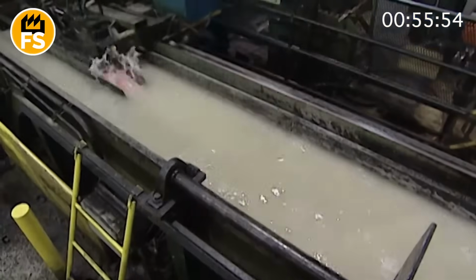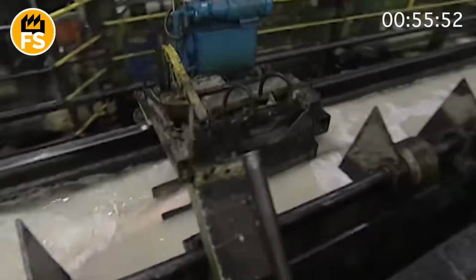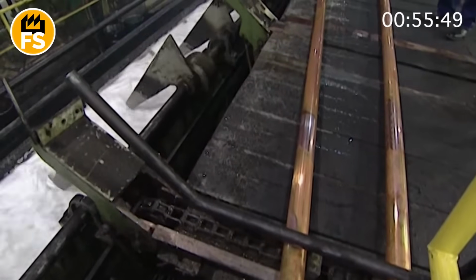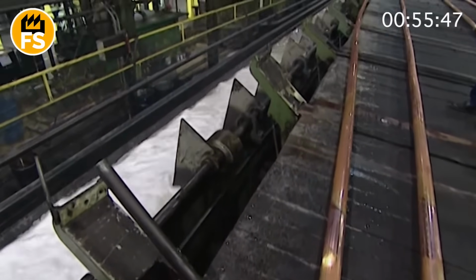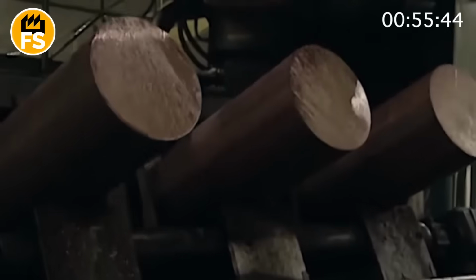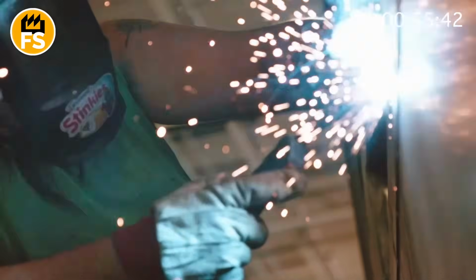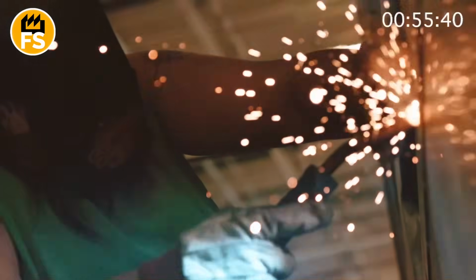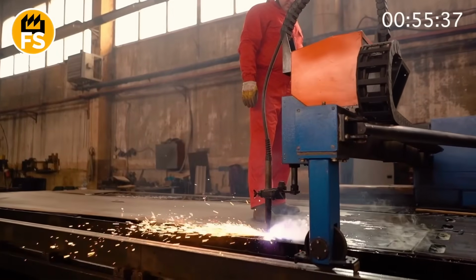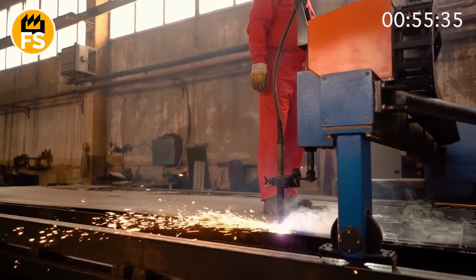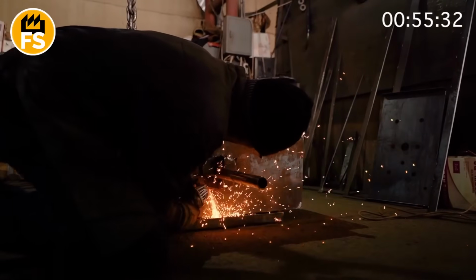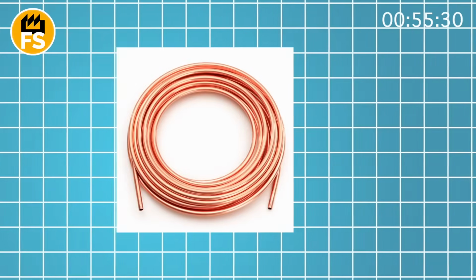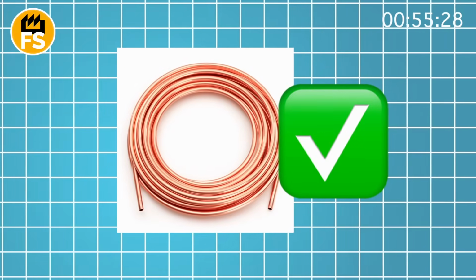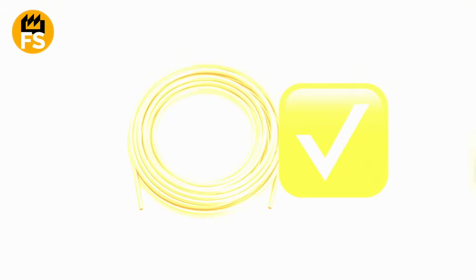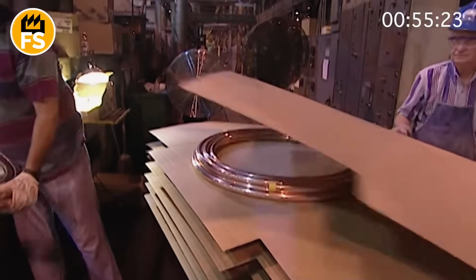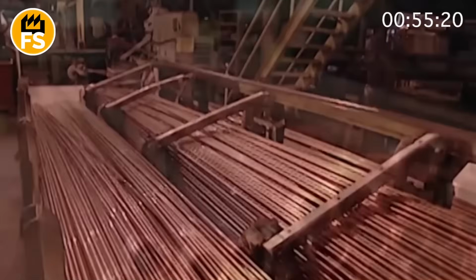Then, the most interesting part begins, checking the dimensions. The tubes pass through special calibrating devices. This can be a set of rings or sensors that measure the pipe. Each ring corresponds to the exact inner or outer diameter. If the tube passes through the ring without problems, the size is normal. If not, an automatic sensor signals, and the operator stops the process. If the pipe meets the standards, it is sent further, for cutting or packaging. If not, it is returned for rework or recycled to prevent defective products from reaching the customer.